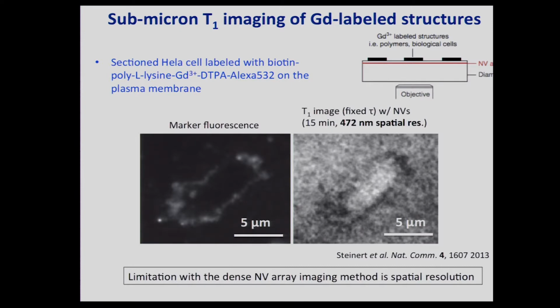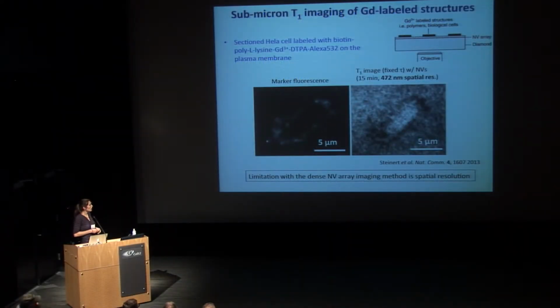And then they took a T1 image. This cell, by the way, is sitting on top of a piece of, again, a piece of bulk diamond in this case. Again, nanodiamonds are not quite there yet for the sensitivity. So it's sitting on top of a piece of bulk diamond. This image is basically probing the NV centers and looking at the relaxation time. And one sees that you get a dark feature where the relaxation of the NV center is increased in the same region where you see the fluorescence, confirming that one can do T1-based imaging.